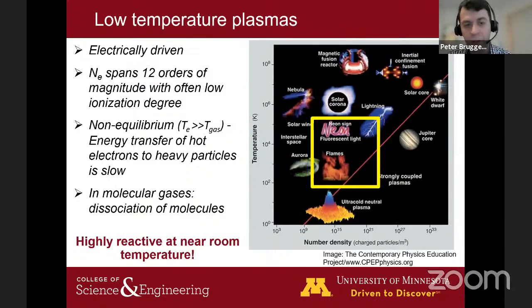The reason why this is unique is that we have a non-equilibrium. I will get back to that briefly in the next slide. You can generate these reactive species, or get a reactive species distribution, out of equilibrium, where normally you would need very high gas temperatures to achieve that. Here you can sometimes even create it at room temperature. That opens a large range of new applications, particularly for treating heat-sensitive substrates or materials.